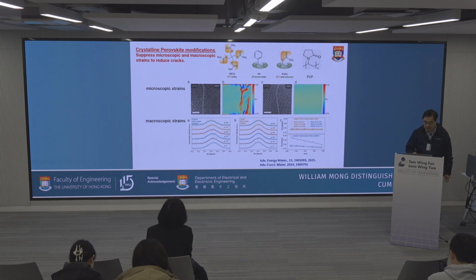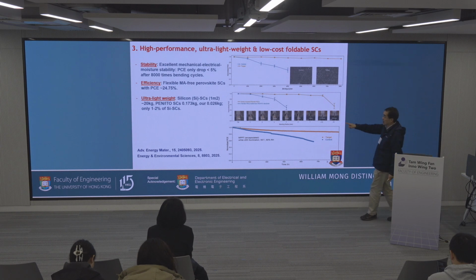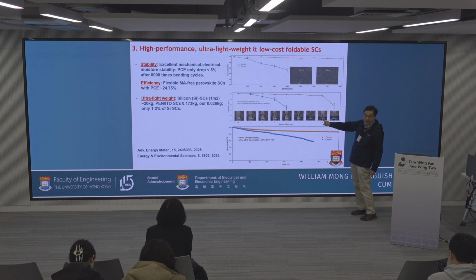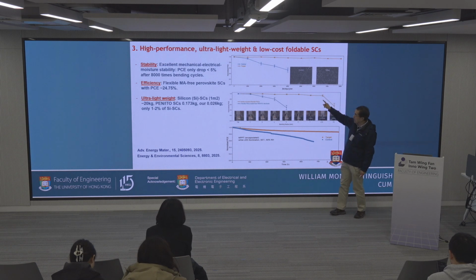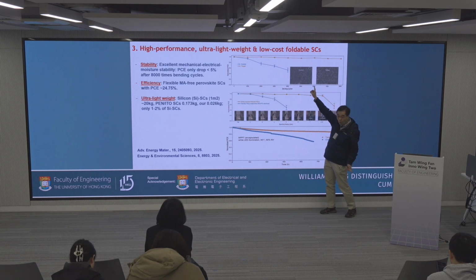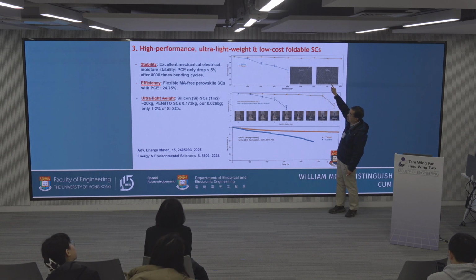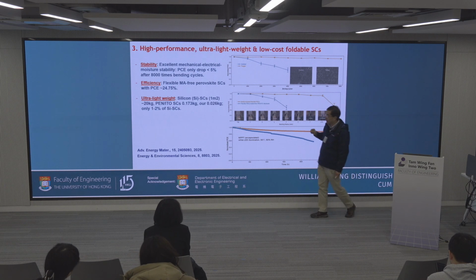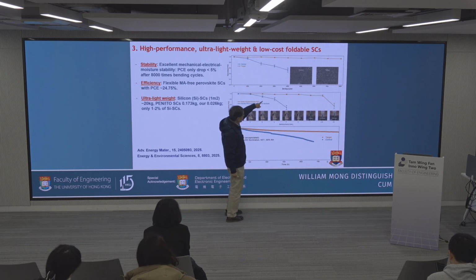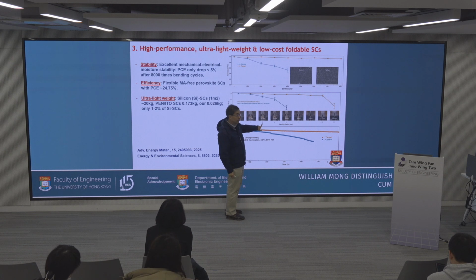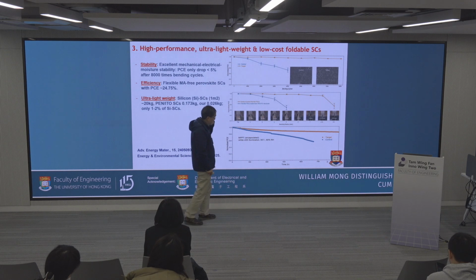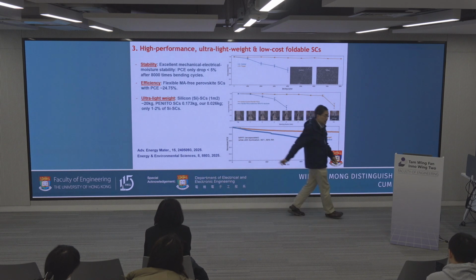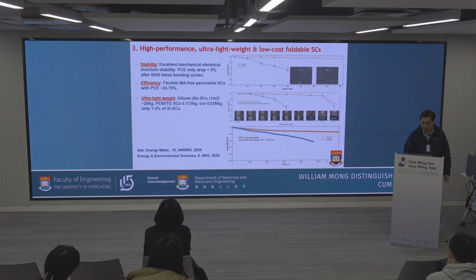This demonstrates that we release the stress and are able to make a perovskite solar cell, this time with bending radius less than 0.75 millimeter. We are here. So we don't have any crack of the perovskite, nor the electrode. The electrode, we replace it with our composite oxide silver wires. So all the structure that we make is reasonably good for a foldable device. Compared to the control, we take a look at the 5 millimeter flexible testing. It is already degraded. So we are about 1 order of magnitude better than the conventional. Not just the mechanical properties, eventually our operation stability also improved.